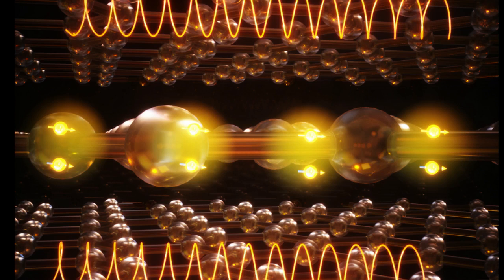a phenomenon that is highly unusual and not known to occur in conventional spin-singlet superconductors. They also observed that after re-entry, superconductivity persisted up to 10 Tesla, the maximum field strength that the lab's magnet could produce.